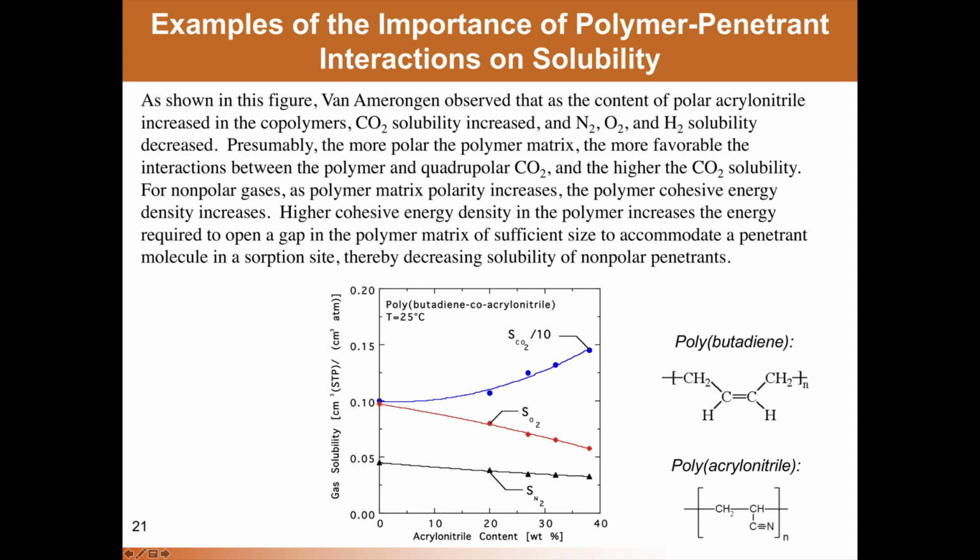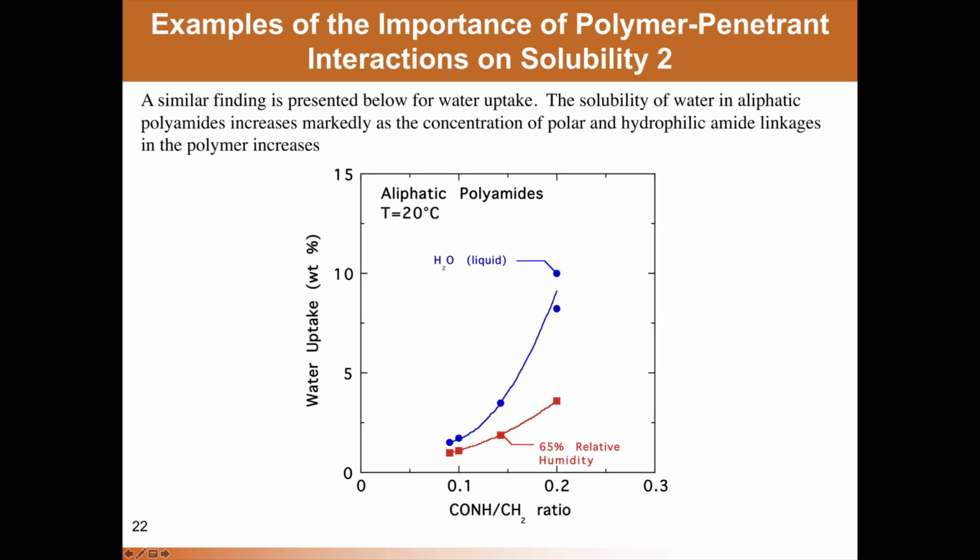So CO2 bucks the trend that you see with gases that can't undergo specific interactions with this particular polymer. Another example is shown here. Polyamides have amide linkages that are very hydrophilic, and as the ratio of amide linkages to aliphatic or hydrophobic linkages in these polymers increases, the water uptake goes up significantly.